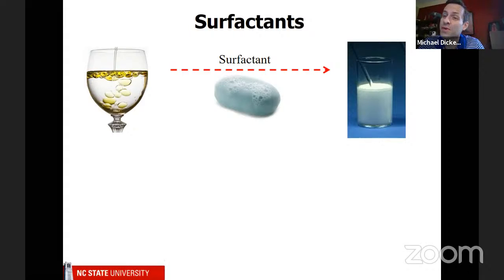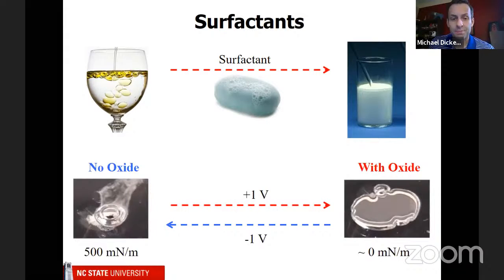So as from experience, it's very easy to put the soap into the water, but it's very difficult to get it to come back out. In fact, it's nearly impossible without doing some chemical processing. Well, in our case, with the liquid metal, we can apply 1 volt and we deposit the oxide layer. And so with the oxide, it acts like very low surface tension. And then when we remove it using -1 volt, remember it beads up and it's got this very, very large surface tension.